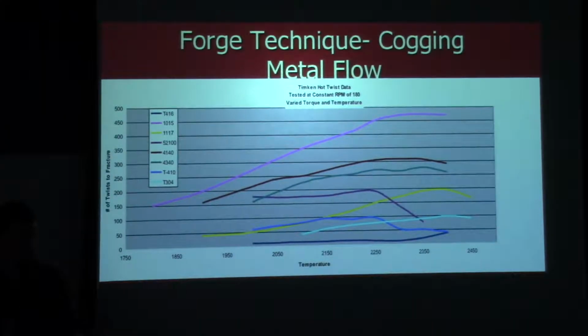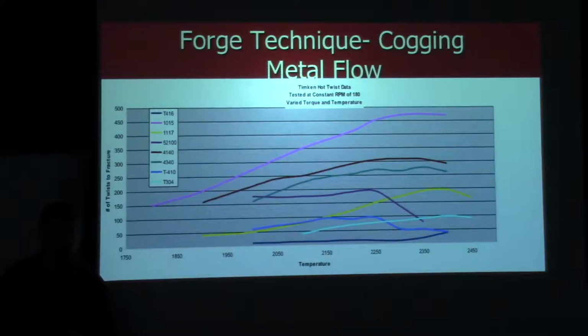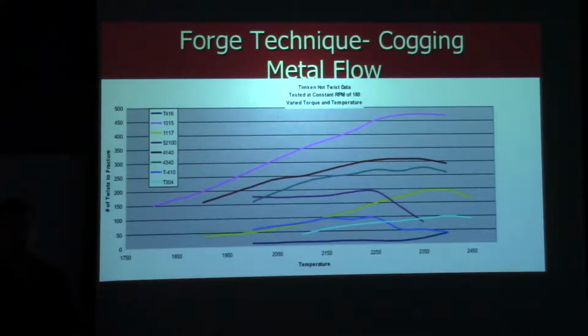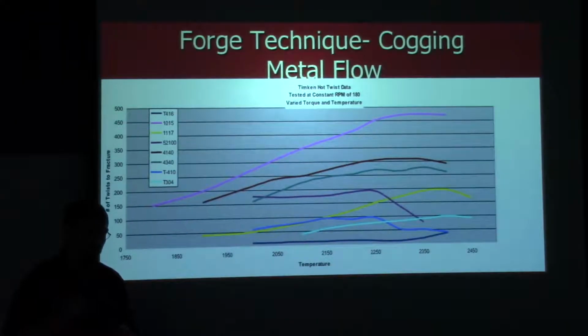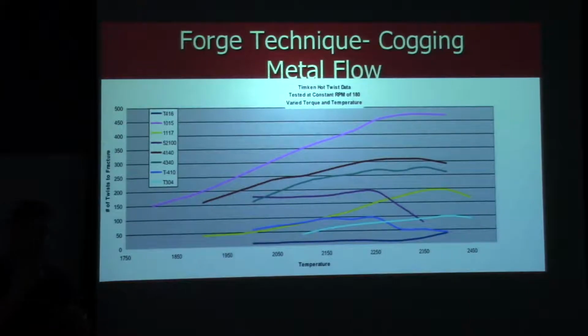What's happening is you're still forming manganese sulfides. In fact, in these grades, they actually boost the manganese as well to make sure you've got plenty of manganese sulfides. And when you now have an object that you're taking to a machine shop and it's made from one of these materials and they go to start cutting on it, all these little sulfides act as chip breakers, so that when they start to generate a machining chip, it breaks off into a nice small little chip, which is great because then it doesn't get wrapped around the chuck. It can cause real long stringers, which can be really hazardous. So it allows the machine shops to be more efficient with their machining setups, use faster speeds and feeds. So it's great if you're doing a lot of machining.